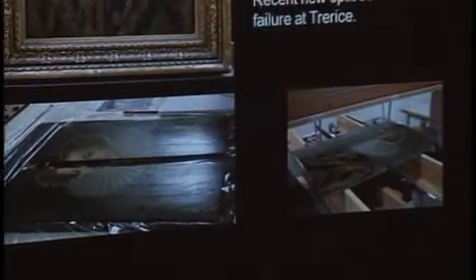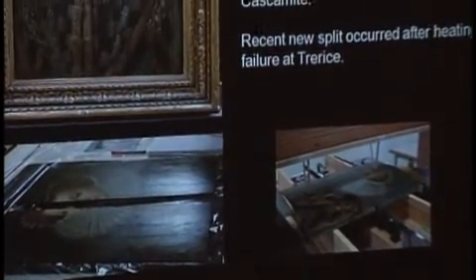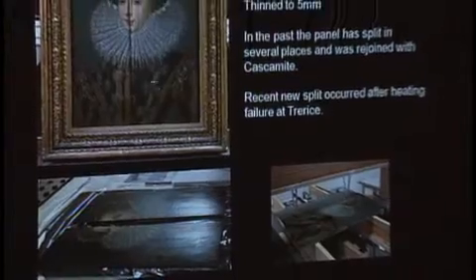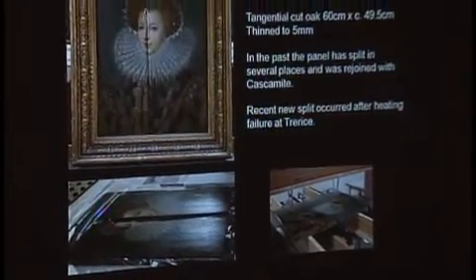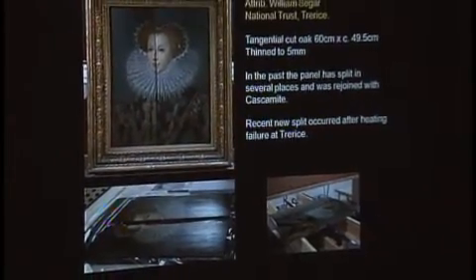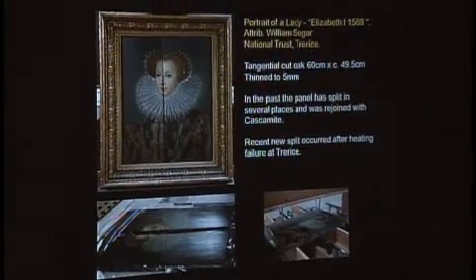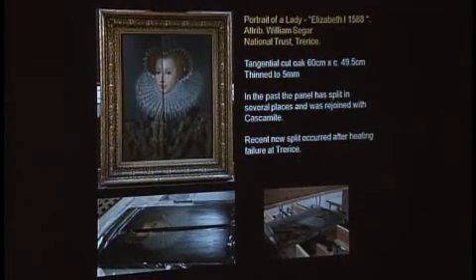This time when the panel moved due to failure of the heating conditions, so the RH went down to 30%, this panel tried to move and hit the frame, and the original plank joint split along the original hide glue joint instead, taking away some of the original paint. So these are the problems that we see, just to put in perspective why I'm looking at this sort of gap filler. Here is the panel in our studios being prepared at the time using the method that Ray uses, and Ray came at the time to come and work with us with this particular panel.